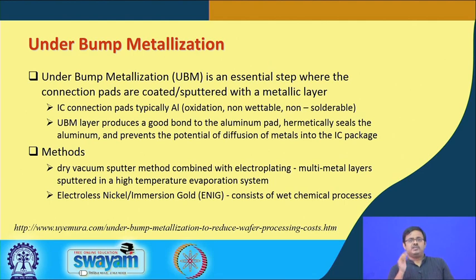Now, what do we do to have this metallic layer deposited on the aluminum or copper connection pads? Okay. So, the first one, which is most common, is a dry vacuum sputter method. So, you take this silicon and then you have this metal sputtering process in an oven, combined with electroplating. In a high temperature evaporation system, you have multiple metal layers that are sputtered and therefore deposited on these pads, typically made of aluminum or copper. Okay. That is the most common method of under bump metallization or UBM.